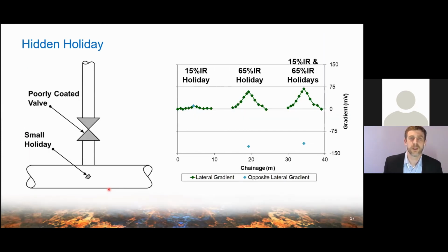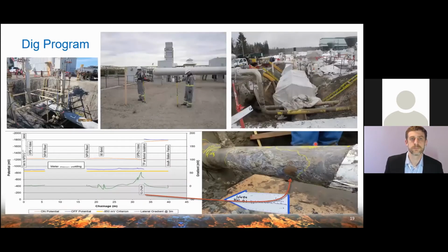All right, so this is a diagram just illustrating the scenario we talked about. We've got a small holiday. Let's say it's a 15% IR holiday. Then we've got a poorly coated valve here. So here's my main pipe, my T to my lateral. And this is what the data might look like. If I only had my small holiday, then I'm going to have a coating indication like this. It's a little peak with my aqua on the same side. If I've just got that big holiday on the poorly coated valve, it's going to be a much bigger peak and I'll have a cross gradient there. Now, if they're both there, you can see that there's actually very little difference between the two cases. So I add both holidays and it's basically indistinguishable. So then you need to say, well, what is the significance and treat it appropriately.